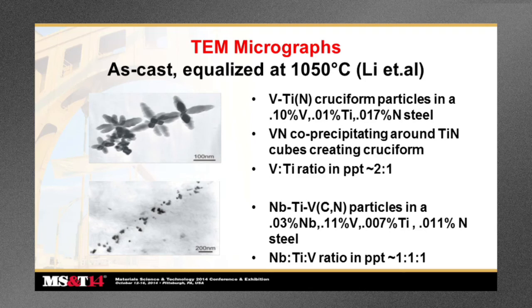Again, taking vanadium and nitrogen out of the system in the austenite, where it will not be effective for strengthening. Similar things happen when you combine a niobium and titanium system. You get these precipitates here, at somewhat lower magnification. These are also relatively large precipitates that don't effectively contribute to strength, and they remove the microalloy that you've added from solution in the austenite, therefore not contributing to precipitation strengthening of the ferrite.